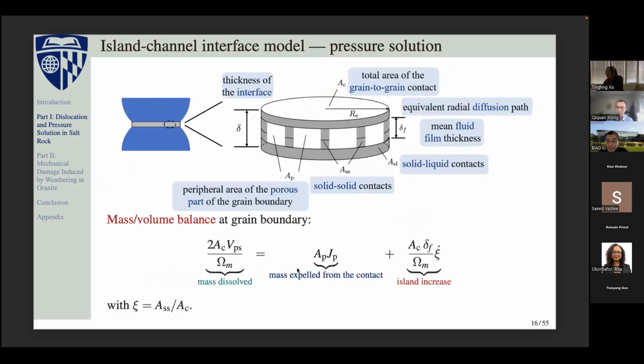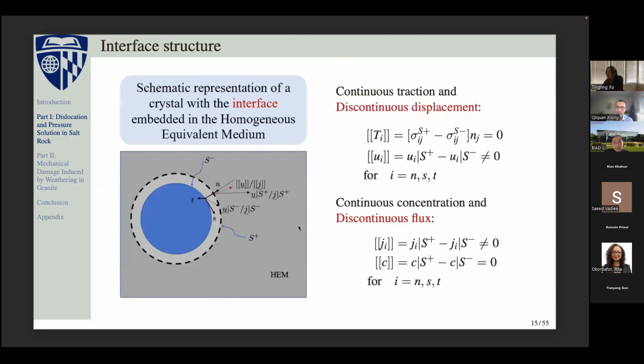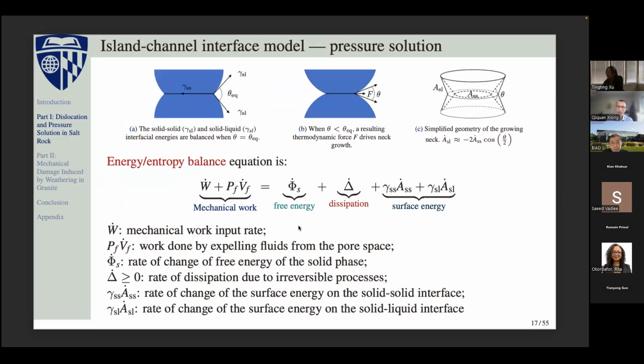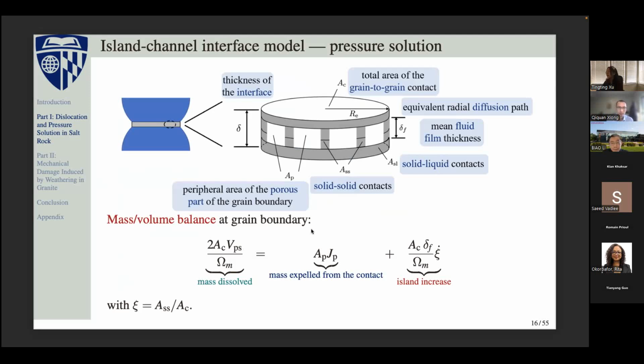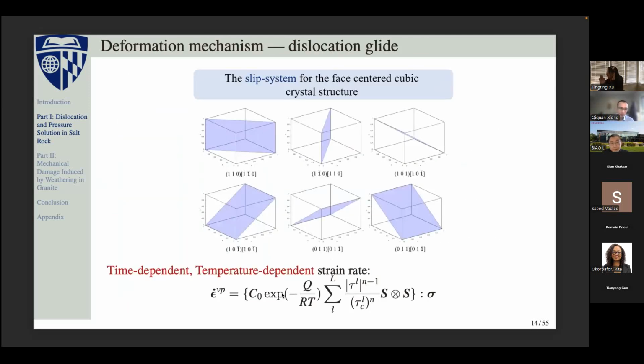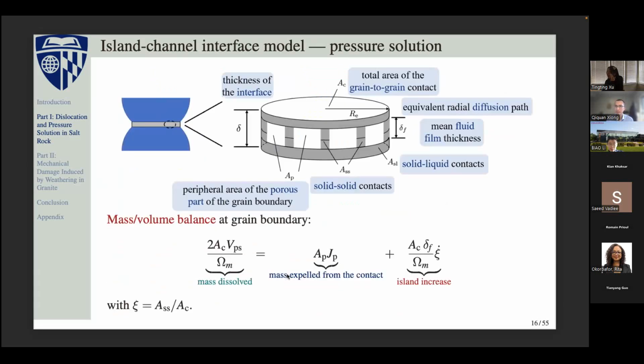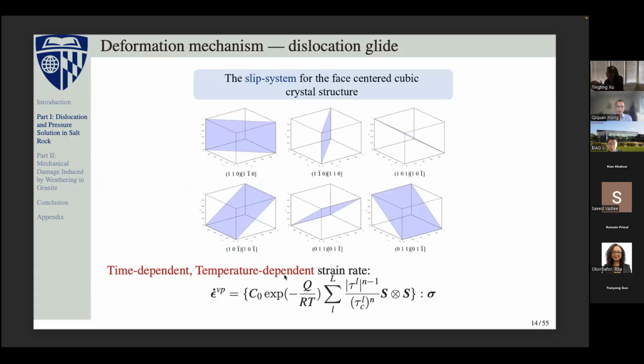I didn't show it in the slides, I think. But you can see that it's very similar to dislocation. For dislocation, we have the viscoplastic strain rate. Oh yes, here. So in the pressure solution part, at the end of all these balance equations, I also have the viscous strain rate related to stress. So they share a very similar formulation. That's why we can cascade into the viscoplastic Eshelby formulation. That means with a constant stress applied, I can also have the pressure solution happen. So that's how we explain this as a time-dependent behavior.